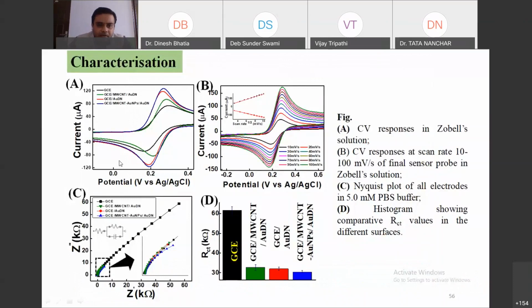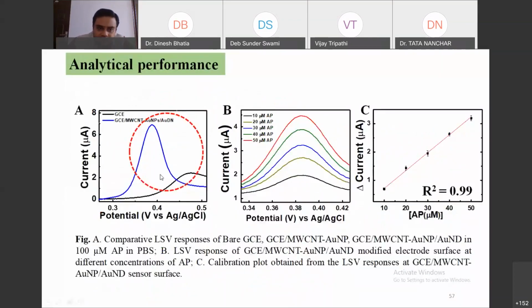So again, in this case, what happened? We have again checked the performance of the chip where the maximum signal was obtained with the nanohybrid comprising the 3D nanodendrites. And again, in this case, the resistance is least with the nanohybrid containing the 3D nanostructure, which is a dendrite. So we have checked the performance. You can see the glassy carbon electrode is here, which is a bare electrode. There is no modification. After the modification containing all the materials, as I said earlier also, the signal is completely improved. And there is a shift also towards the negative potential. It shows that electrocatalysis is happening.